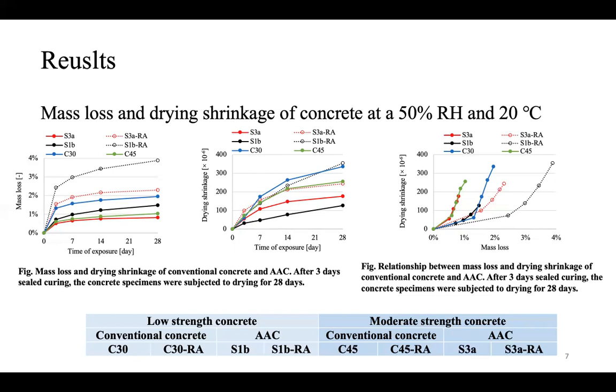It is also interesting to see that the curves of conventional concrete almost coincided with that of alkali-activated concrete when natural aggregates were used. It implies that for concrete with natural aggregates in this study, reaching a certain drying shrinkage was a matter of time, just depending on the point when a certain mass was lost.